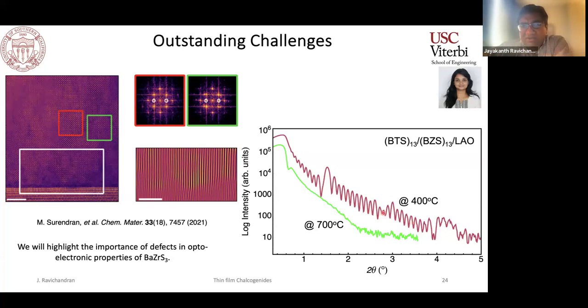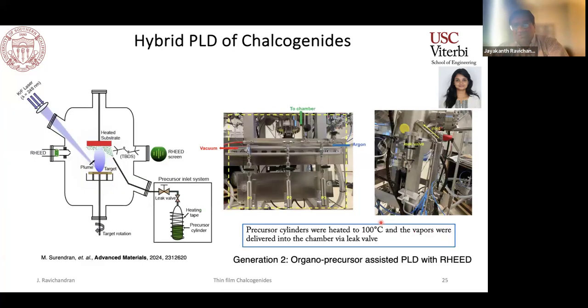So there was a catch-22 here where we tried to increase the temperature to get crystallization, but then the interface abruptness goes away. So we thought we'd take a step back and see what other techniques one could use to solve this issue. And this is when we started talking to Professor Bharat Jalan at Minnesota, who had developed a lot of these hybrid MBE type techniques. And we started trying to incorporate the sulfur precursor using a metal organic or organosulfur precursor instead of our argon H2S to see if that resolves some of the issues that we are seeing here.